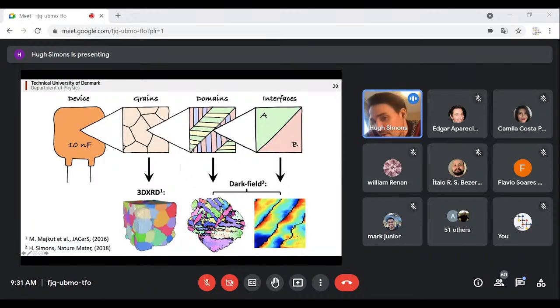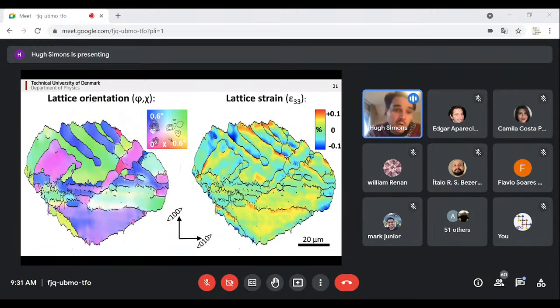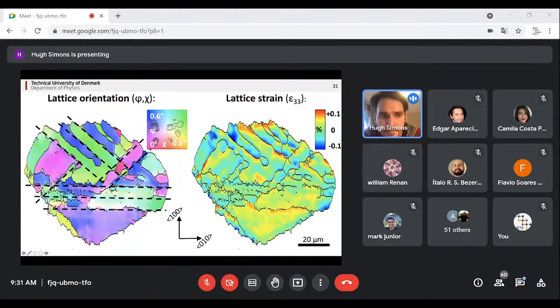And this is where we think dark field microscopy could be something really useful. And this is exactly the study we did. So we looked at this one grain and we were able to visualize the lattice orientation due to the different domains and also the lattice strain that's associated with this. At first thought, this makes a lot of sense. You have domain walls that fall along 110 type lattice directions, and also these ones, which are also at 110 lattice directions, but going at 45 degrees into the screen.